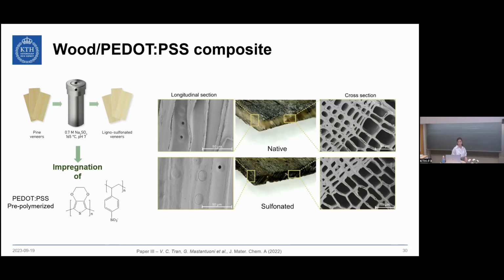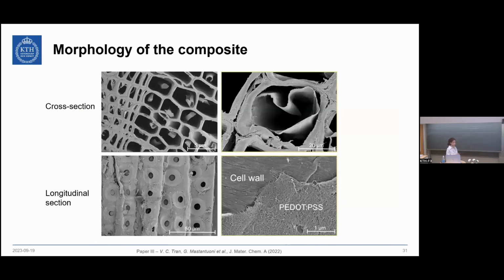This is quite difficult to spot, so what we used was critical point drying, which partially solubilizes the polymer to actually peel it off from the wood structure and to observe its morphology. We could first of all see that the polymer is present in all the lumens, which proves the very good infiltration, and that it was laying as a very thin layer on top of the lumen surface. From the longitudinal section, we could also see that the polymer, which looks very different from the directional microfibril in the cell wall, is still deposited as a continuous layer. And a uniform morphology, as well as a continuous layer, is argued to actually improve the electrochemical properties. And the reason for this is that then the charge can move more easily if the morphology is smoother.